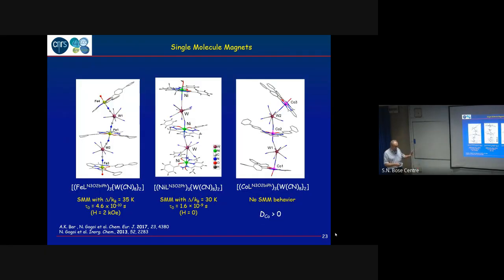So just a picture to show that it's quite easy to make polynuclear systems that behave as a single molecule magnet. So here I show a trinuclear system that is obtained by reacting the complex I have introduced before with a cyanometalate. Here it's with a tungsten cyanide. So this center has a spin half, and when you react it with the iron complex or with a nickel complex, you get the same kind of compound, and these compounds behave as a single molecule magnet. So this is just what you expect.